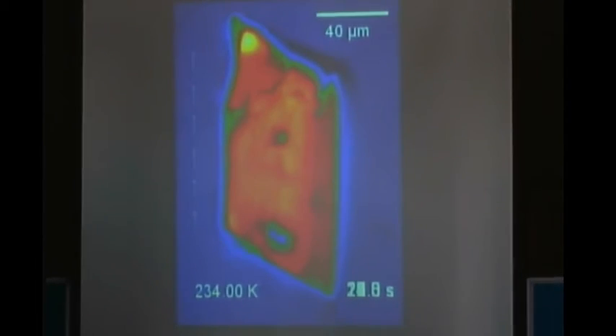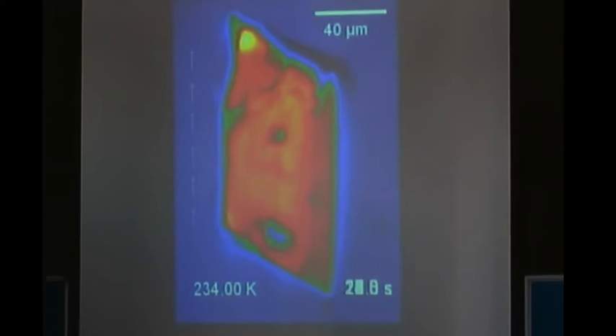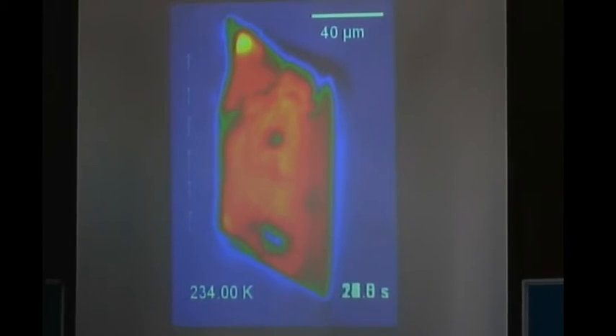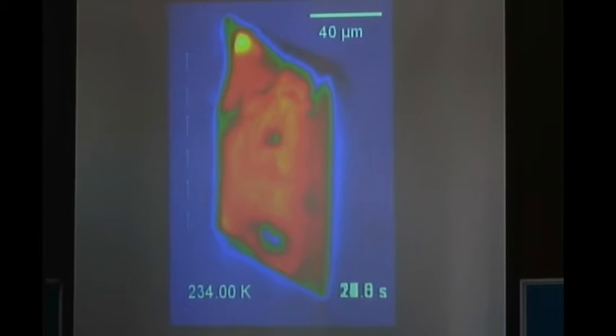And then we said, what happens if we put a defect here, just here? By laser ablation, we put a defect. What is the effect of the defect? Because our interactions are elastic, that means that the local strain and the defects may have an important role in the nucleation and growth. So we took exactly the same crystal, same nucleation and growth, and we put a defect here, and we tried to make the experiment. As you have seen in the beginning, without the defect, you have the nucleation and growth in this direction. It goes from this part to this part here. And now here with the defect, just check here.